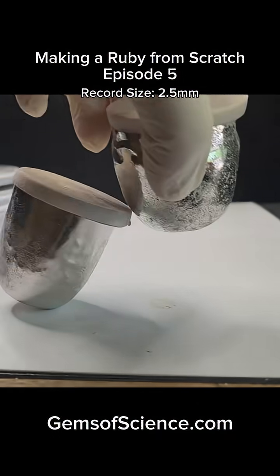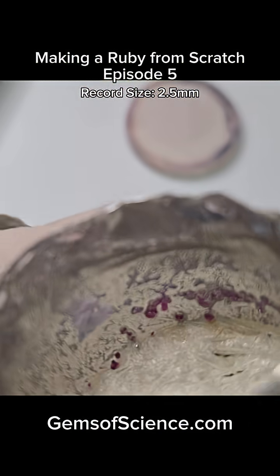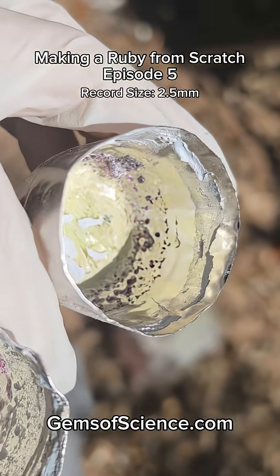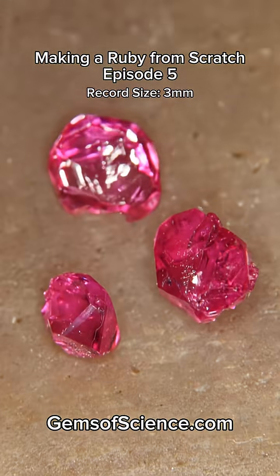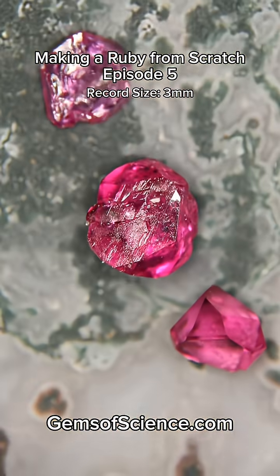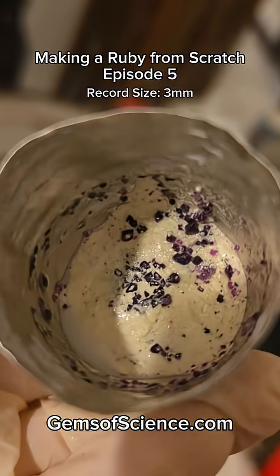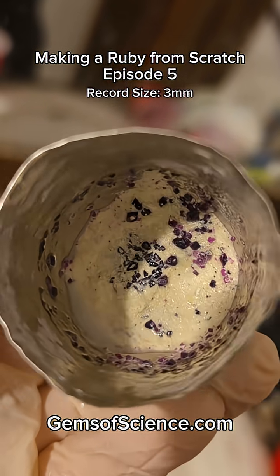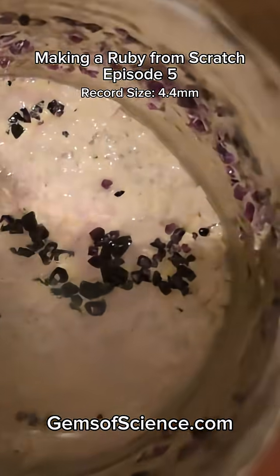And this time, something amazing happened. Both of them had big, beautiful rubies. The lithium run brings the record up to 3 millimeters, with gorgeous pink-red crystals that are less platy and better shaped. But the tungsten run was crazy. There were even larger crystals hiding under the surface, bringing the final record for this episode up to 4.4 millimeters.